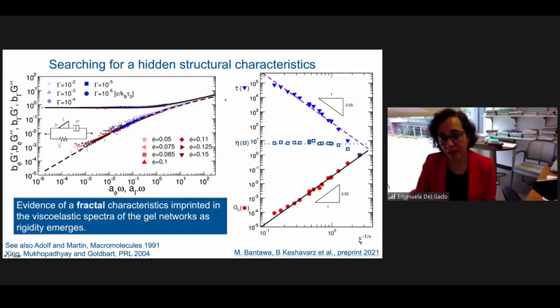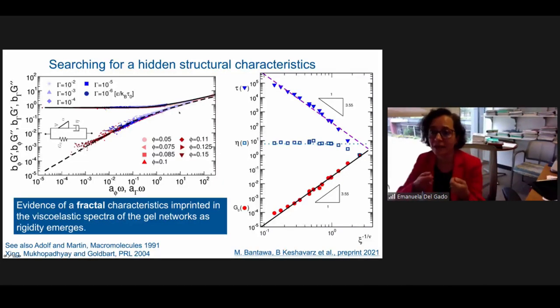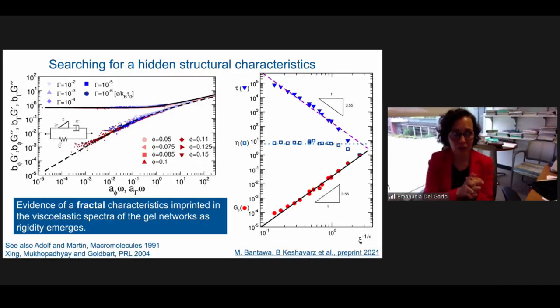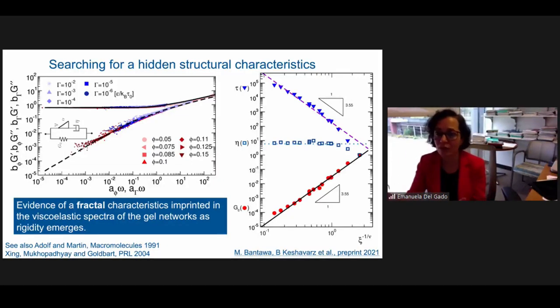And this common viscoelastic behavior, which can be recapitulated by a unique viscoelastic constitutive model, has some interesting characteristics. One of these is that there is an extended power law regime, which we think is very important. In fact, it corresponds to the need of having a fractal element in the constitutive behavior. This type of power law behavior is typically associated with the presence of a fractal structural characteristic in the network. But these network structures that we have are actually never fractal. They don't show any fractal nature if we just look at the amount of particles that are there and how they're spatially organized.